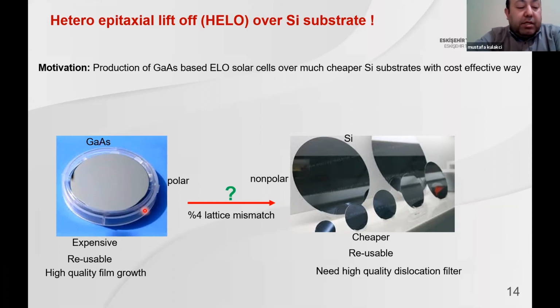So we think that maybe it can be lifted off from silicon templates, but there is an obstacle, of course. One of them is a polar material, the other is non-polar. There is a 4% lattice mismatch. Also, thermal expansions are very different between them. But when you look from a general perspective, gallium arsenide is, of course, reusable by using the ELO technique, and it is of high quality for epitaxial growth, but silicon is much cheaper. It can be reused many more times compared to gallium arsenide, but you need a very high quality dislocation filter. Otherwise, you end up with defective structures, which kill your devices.